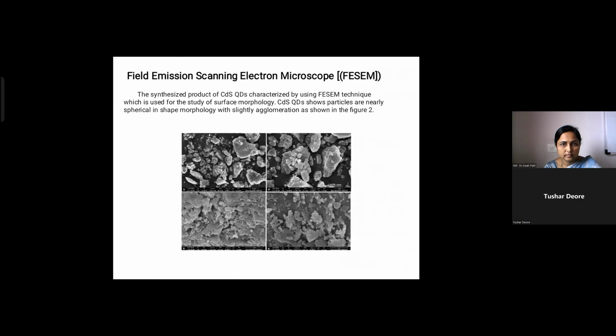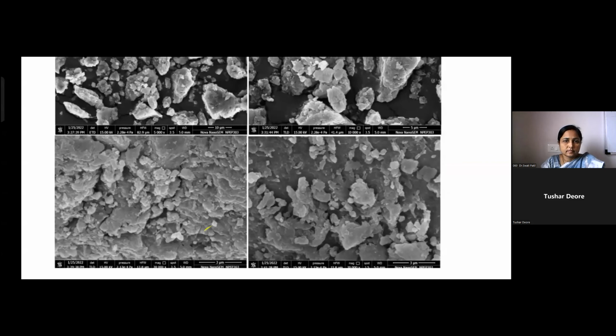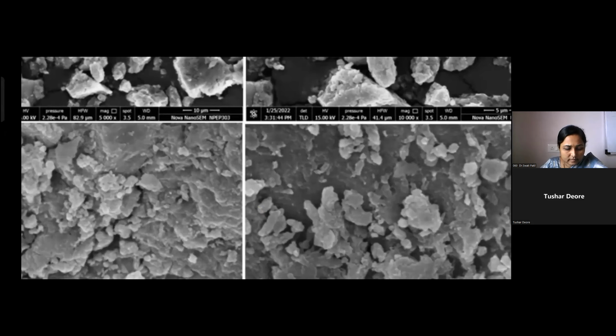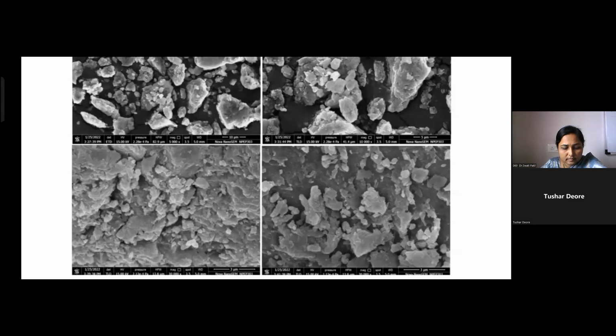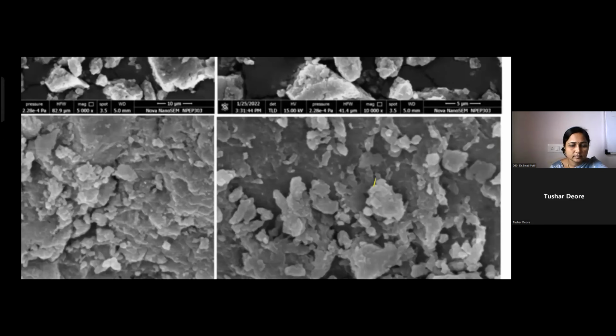My third characterization, ma'am, is field emission scanning electron microscopy. I am taking the CdS nanoparticles at various ranges. The synthesized product of CdS quantum dots was characterized using the FESEM technique, which is used to study the surface morphology. CdS quantum dots are nearly spherical in shape and morphology, with slight agglomeration. We can clearly see.